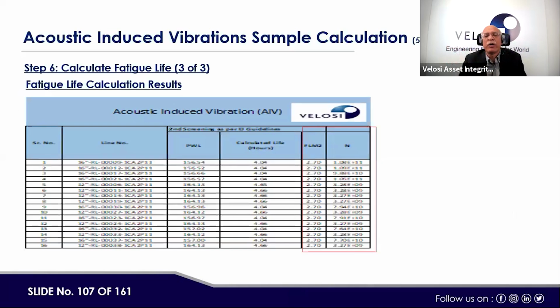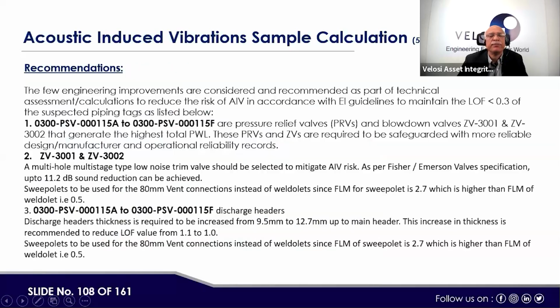So this way we have calculated the fatigue life here, 4 hours for each event. Now, what are the findings and recommendations? We found that the PSV's downstream line required an increase in thickness from 9.5 to 12.7 mm. And for the blowdown valve, the thickness is already quite high, and it is recommended to change the trim of the BDV valves.